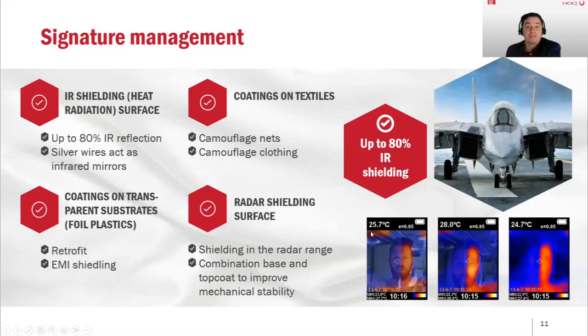Well, and finally, signature management. Well, if we can reflect heat radiation, or if we can adjust the degree of heat reflection, we can also adjust the degree of shielding for other wavelengths. For example, for EMI shielding, the silver wires can be used. It simply depends on the amount of silver wires that is deposited on a surface, and if you want, on the mesh size that you generate with the silver wires. And also in the microwave and radar range, it is appropriate to shield these electromagnetic waves. And the degree of shielding can be adjusted depending on the customer needs and also depending on the target applications.